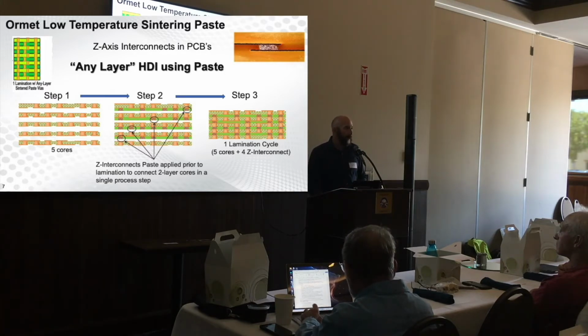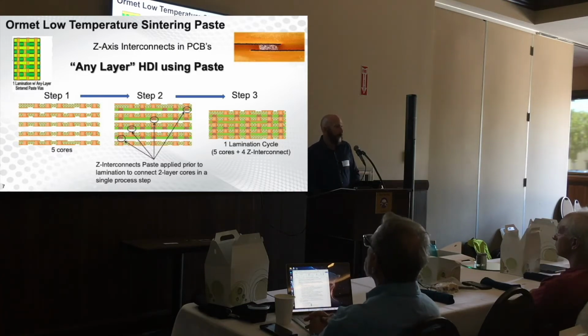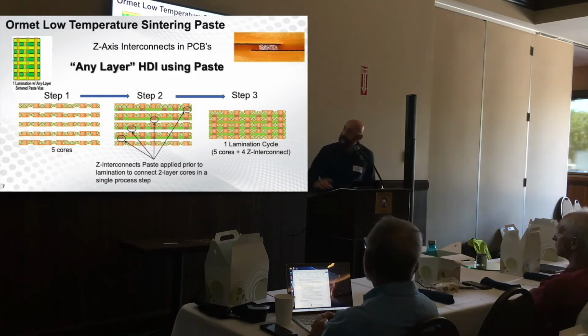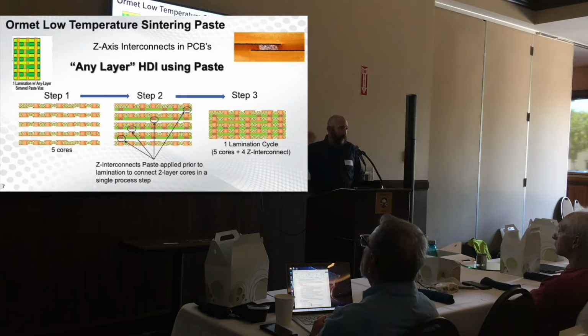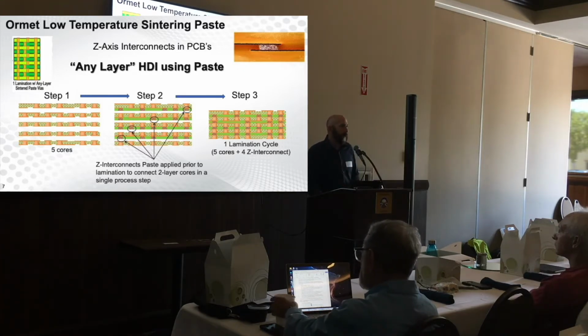Excuse me, you're currently saying that there are 80 layers? Yeah, you can do that. So one common way is to do, for a 72-layer multi-layer, and by the way, this is done in production, you have 18-layer subs that are stitched together. But you could do some number of double-sided subs. In theory, you could laminate them all in one shot and have a very high layer count board and have unrestricted via placement, because you're not taking up that real estate with a via that's going between multiple layers. It has a lot of potential, but like everything else, it has its place. It's not for everything.